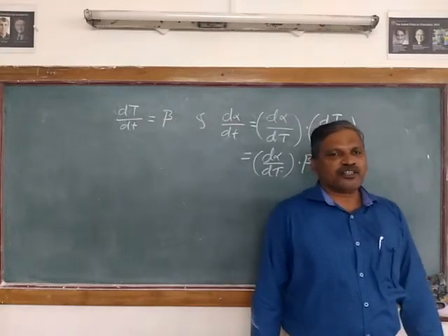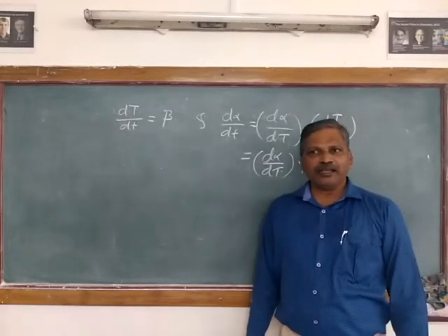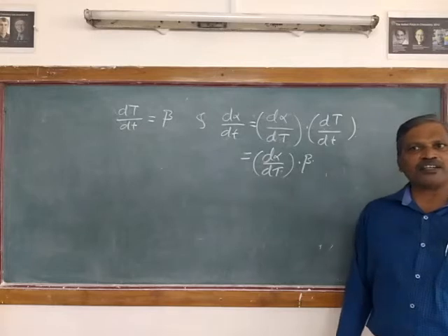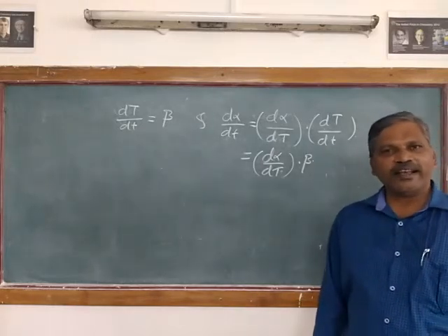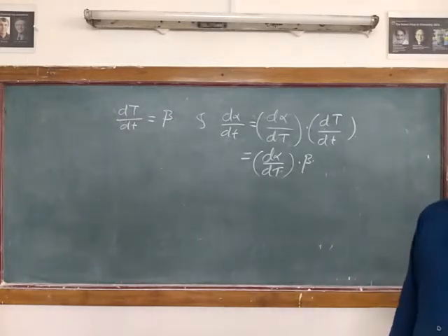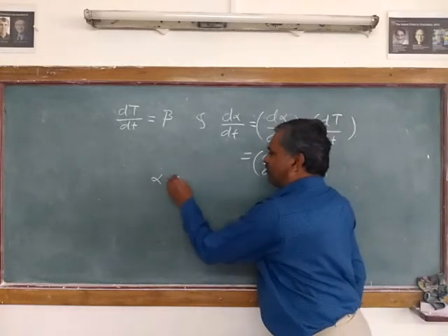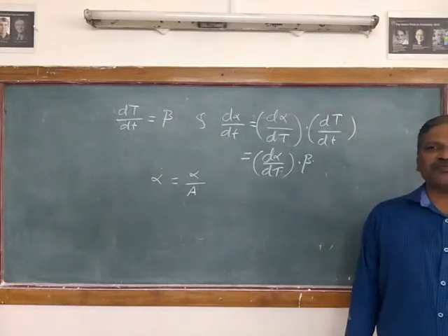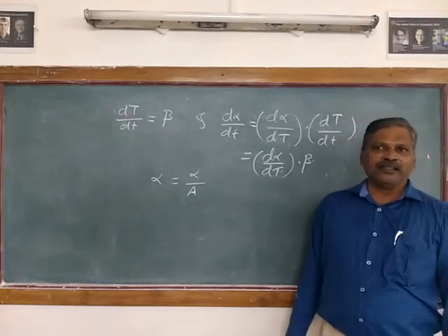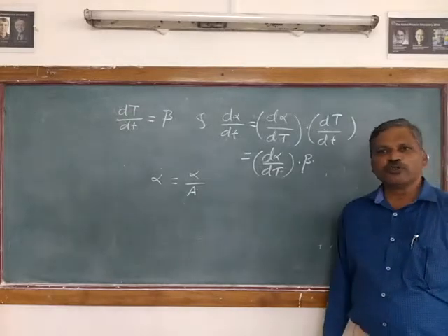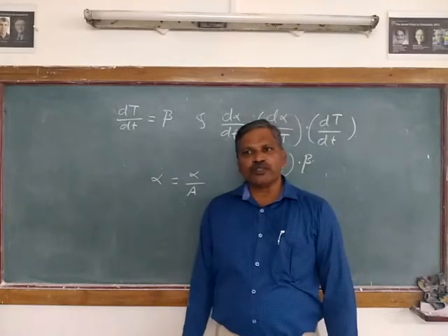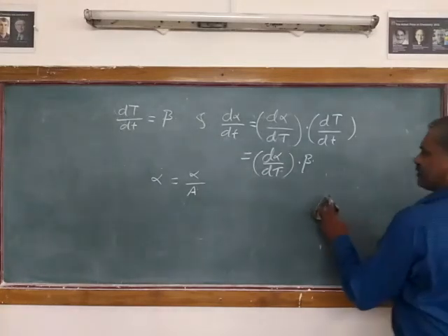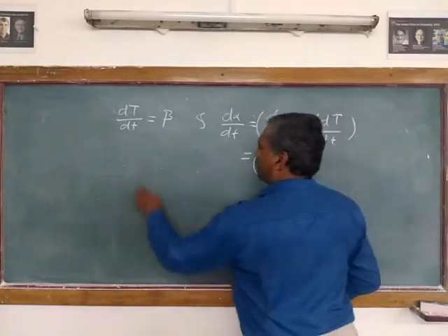For a differential scanning calorimetric curve, if the total area A represents the total reaction over the whole time or temperature interval, and the fractional area, that is small a, gives the partial reaction up to time T, then alpha is equal to a by A. The ordinate deflection Yt in DSC represents the rate of heat supply in joules per second, so we might also use it to find the rate, since d alpha by dt is proportional to Yt.